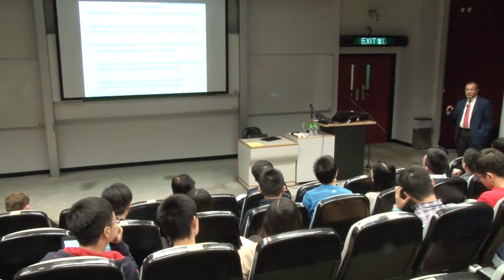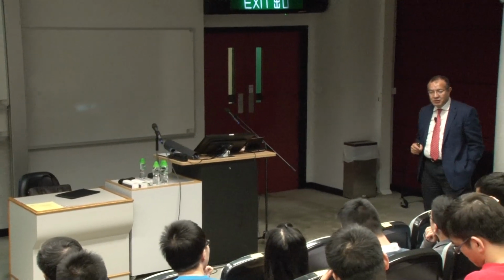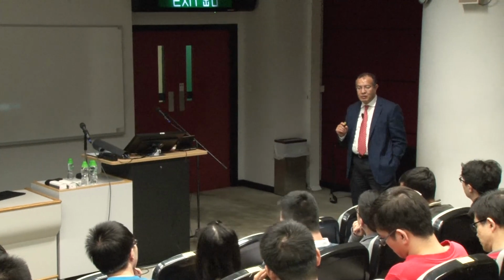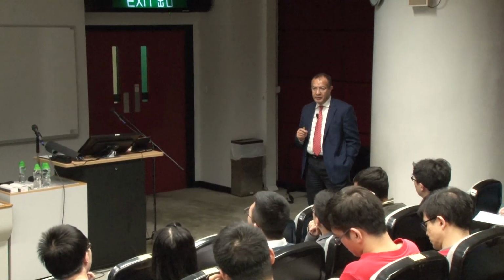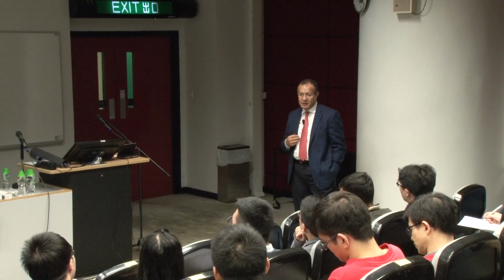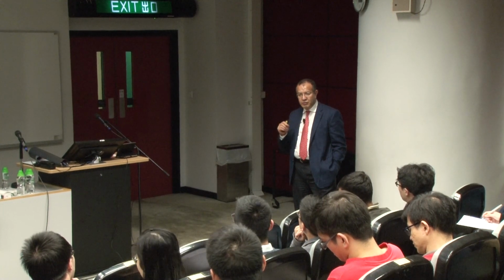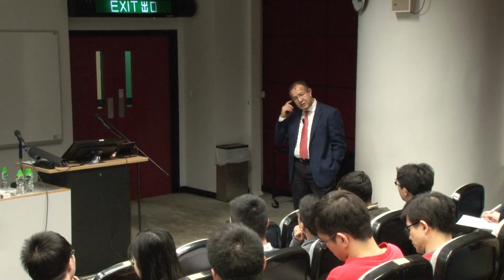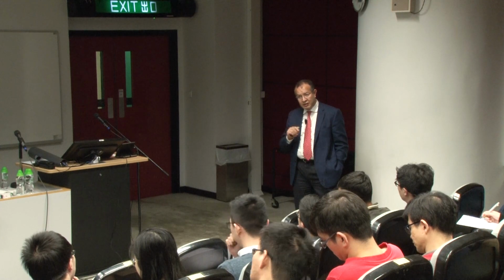Yeah. Well, if we use that electrolyte with sulfur alone, there is dissolution. So obviously, there is something happening with selenium that created this. We don't know what it is at the moment, to be honest with you. We're working on trying to understand it. But when you have selenium, even traces of selenium as a composite, and with the right electrolyte, we did not see dissolution.